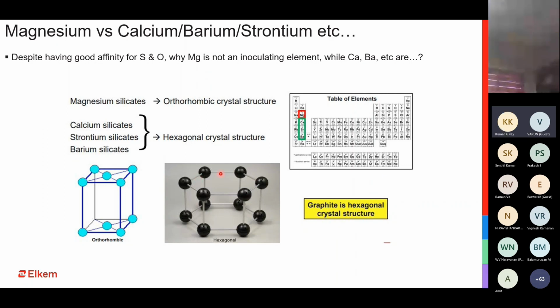So how does it affect graphitization? Graphite has a hexagonal crystal structure. So when graphite, which is a hexagon, and the silicates of calcium, strontium, barium, which are also hexagon, combine together, it ensures that the graphite would precipitate on this type of structure and will find it very difficult to precipitate on an orthorhombic kind of structure. So that is the reason why, despite having a strong affinity for sulfur and oxygen, magnesium is not an inoculating element, but calcium, strontium, and barium are inoculating elements.